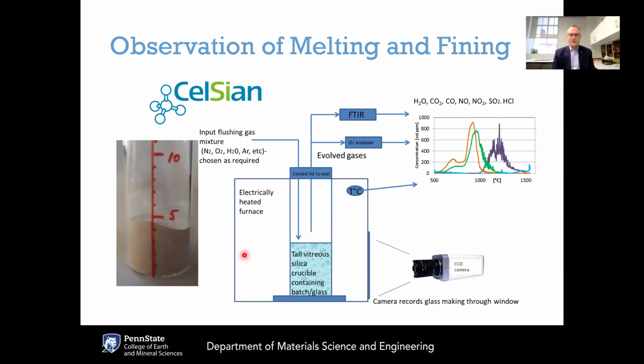We've been working together with CelSian, which is this great company that is based in the Netherlands. They do so much nice research related to glass melting and forming. We've been working with them on the melting side. They have this great setup with transparent crucibles and a furnace that has a transparent window where they can actually take videos of the batch to melt conversion process. So you can see these reactions happening as the batch materials are heated up.